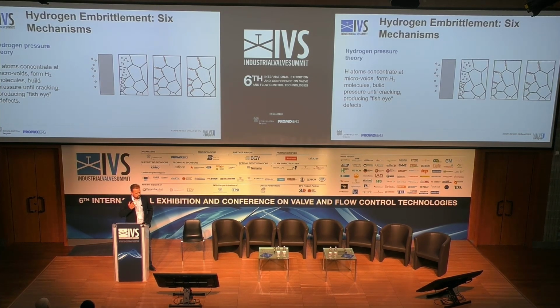So basically what you can see on the image here is that hydrogen starts to penetrate inside the metal. The funny part is that for us chemists, speaking about hydrogen as a molecule is fine. Here we are speaking about atomic hydrogen. Atomic hydrogen by itself shouldn't exist, because it combines very easily to form a molecule. Whenever it becomes atomic, you have a very active species. That activity interacts very easily with your material, and with metals that, in how we perceive them, are very resistant. But this reactivity of a very active gas on top of the surface, combined with high pressure, is what makes this issue such a big problem, because you cannot escape from it. It's sort of a catalytic reaction where hydrogen gets activated on top of the metal.